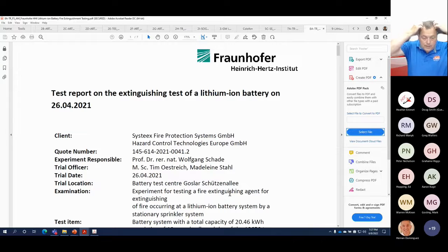What we're doing is putting misting nozzles with a 3% solution of F500 inside the cabinet so that the solution of F500 can flow through into the rack and get on the fire. So we've created a system that does that. The secondary part of the system is the sprinkler head inside the containers, and that's used mainly for encapsulation of HF gas and all the explosive off gases.